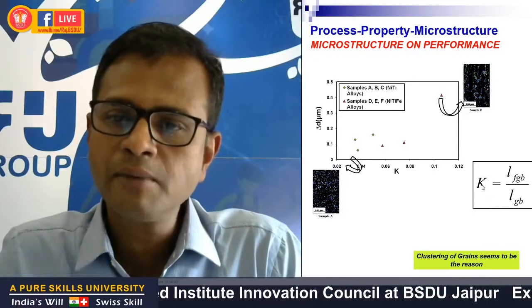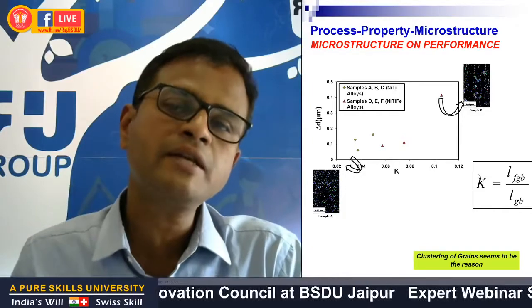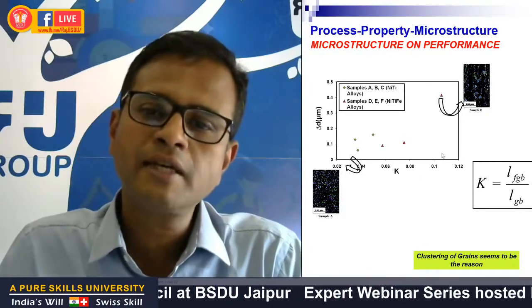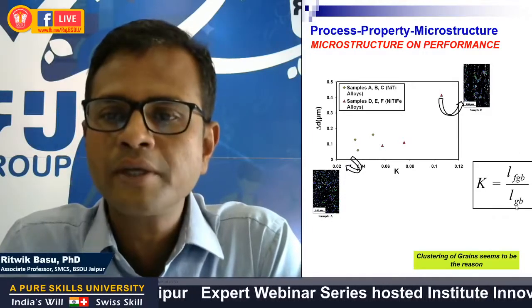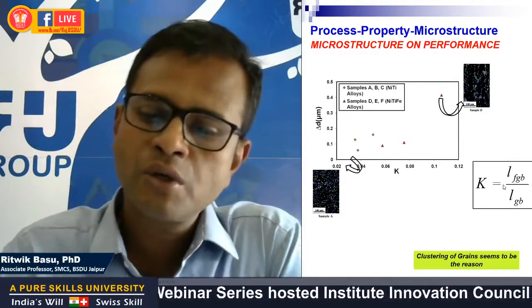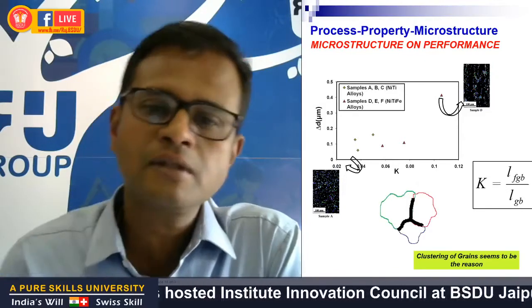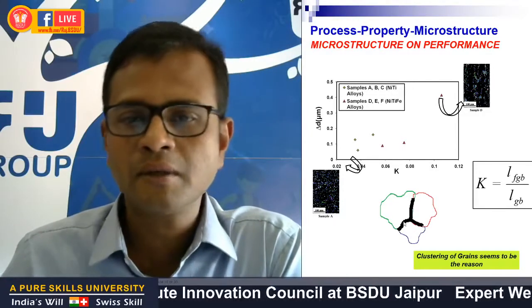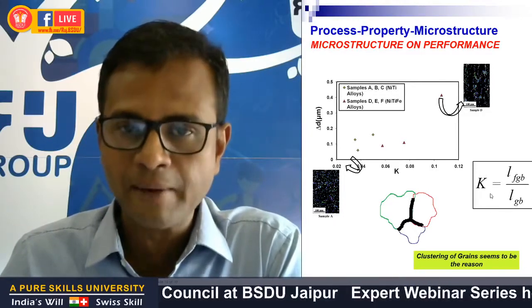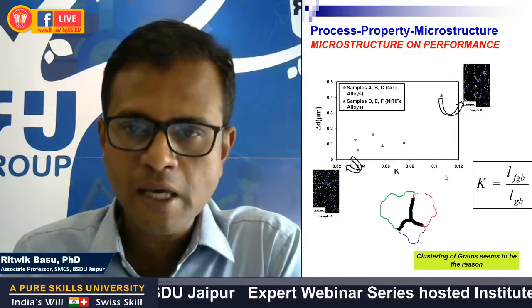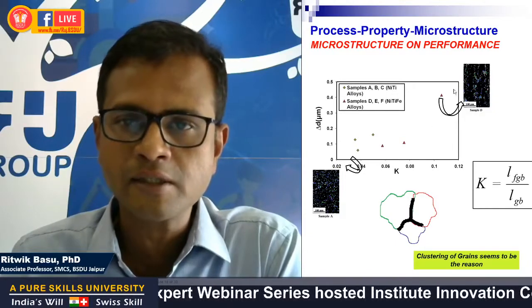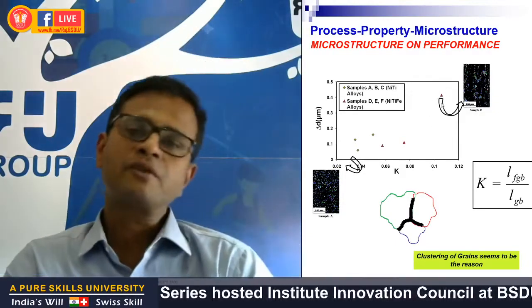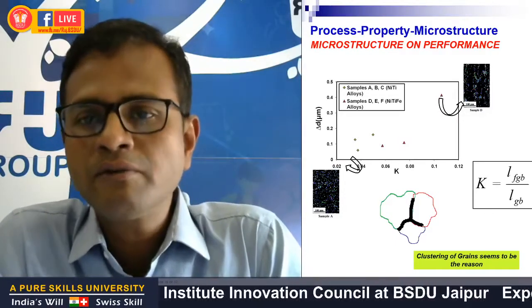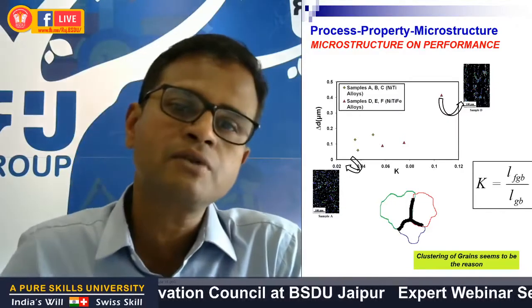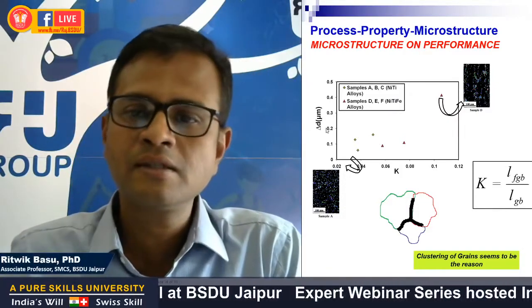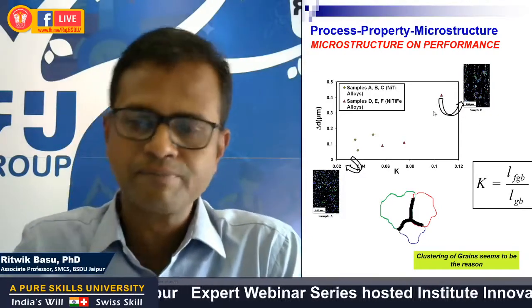So we have found a parameter K that defines the fine grain clustering as a microstructural quantity, and we defined the K parameter as a ratio of the length of the fine grain boundaries to the total grain boundary length in the microstructure. As you could see, with increased clustering of fine grains, the effective fine grain boundary length between the fine grains increases, and that increased the value of K. So the plot of delta D versus K shows a nice correlation, with sample D exhibiting the highest K value. So the first conclusion from this study was that the irreversible strain or the non-recoverable strain, which is indexed with this quantity called delta D, is purely a function of the clustering of fine grains.